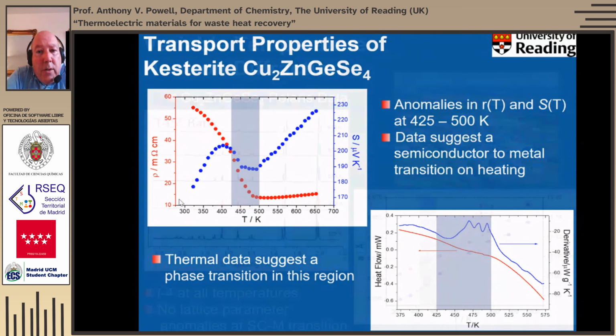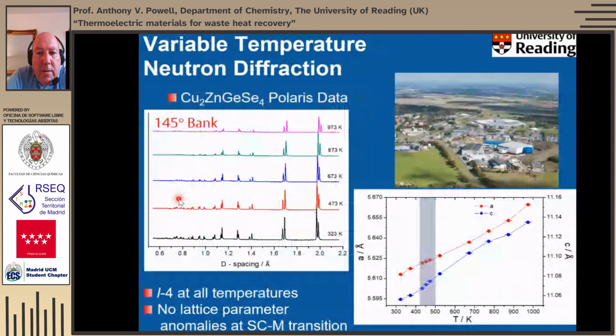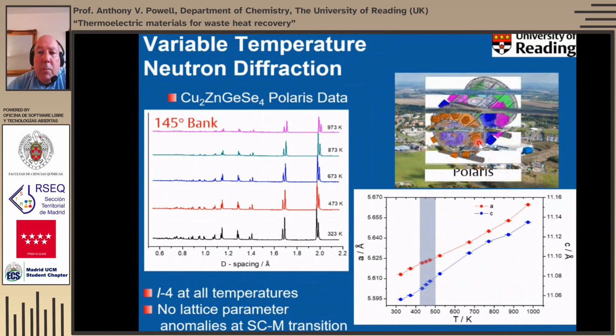But to study this, we took this, Jesús mentioned the ISIS neutron facility, to Polaris, which is an instrument within this aircraft hangar type facility here, one of the Target Station 1 instruments. Polaris is a multi-bank instrument. So this is just one bank from Polaris as a function of temperature. And as you can see, surprisingly, there's very little variation in the neutron diffraction patterns as we heat this up.